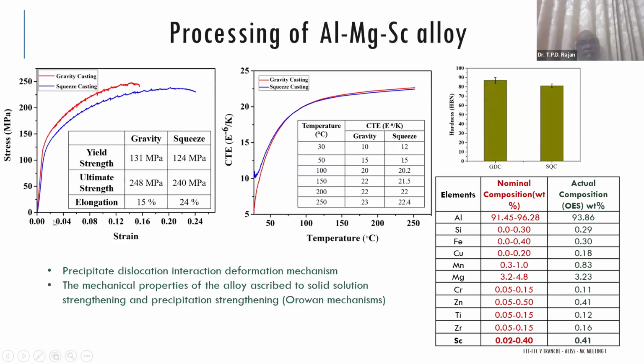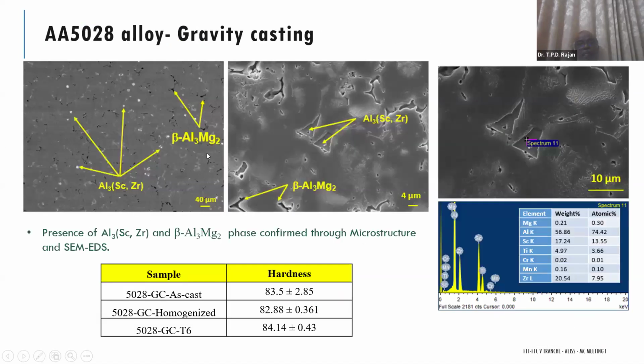So during our initial studies, we had done a lot of optimizations by using the gravity cast plates, squeeze cast plates, and the addition of the scandium into that, and how the properties are getting increased. So we found that the gravity cast plates and the squeeze cast show almost 248, 240 megapascal, but the squeeze cast shows a very high percentage of elongation. And a detailed microstructure also shows the Al3ScZr. Once you have a zirconium phase along with this, it again enhances the mechanical properties.